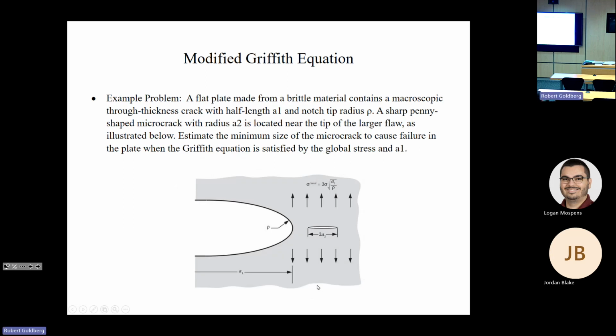So we'll finish this section with a fairly quick example problem. Here's our problem again that we talked about. We have a brittle material, and similar to what we talked about before, we have a big crack with a half length A1 and a radius of curvature rho. And here we have our mini crack, right to the right of it with its own crack length, located near the tip of the larger flaw. So what we need to find is the minimum size of this micro crack. What's our value of A2 that's going to cause this mini crack to grow to the point where it'll then link up with the big crack and overall cause failure?